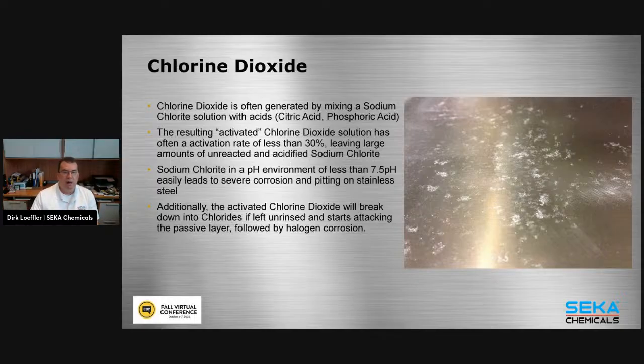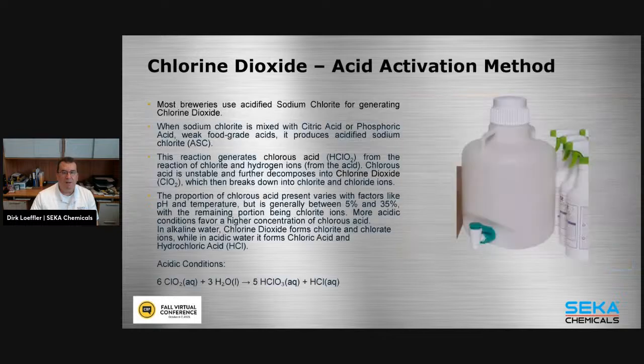leaving you with a very large amount of unreacted sodium chlorite in a very acidic environment. Okay, so the result is this one here, and I've broken this down a little bit for you guys. Sodium chlorite is mixed with citric or phosphoric acid. It produces acidified sodium chlorite, and this reaction generates chlorous acid, which then forms chlorine dioxide, because chlorous acid is unstable and it actually decomposes into chlorine dioxide.